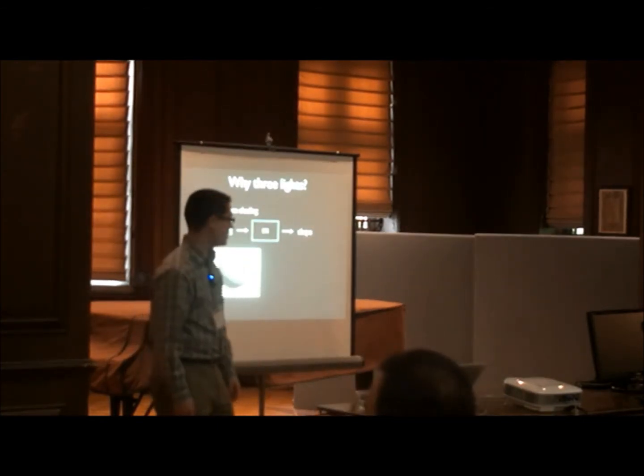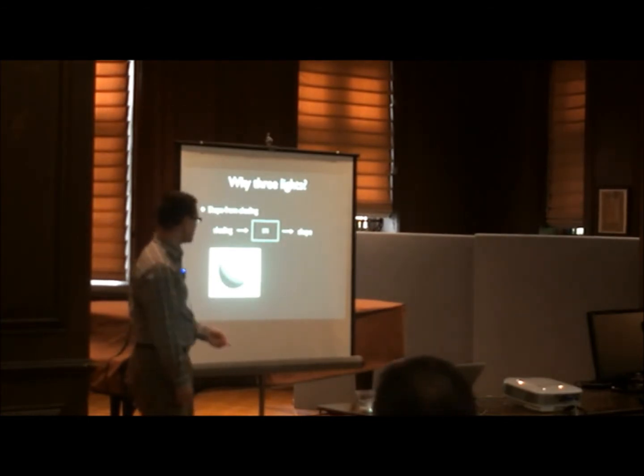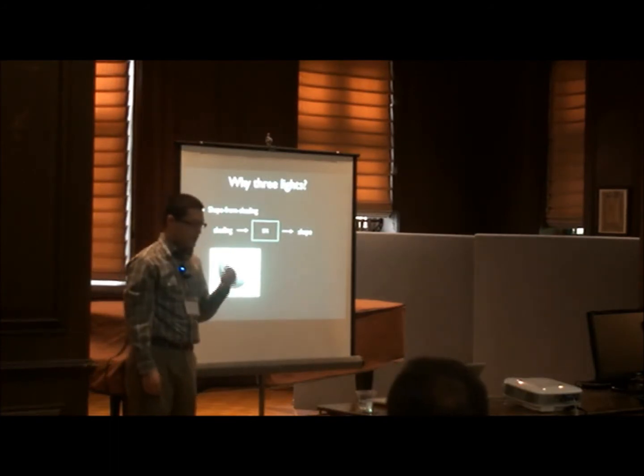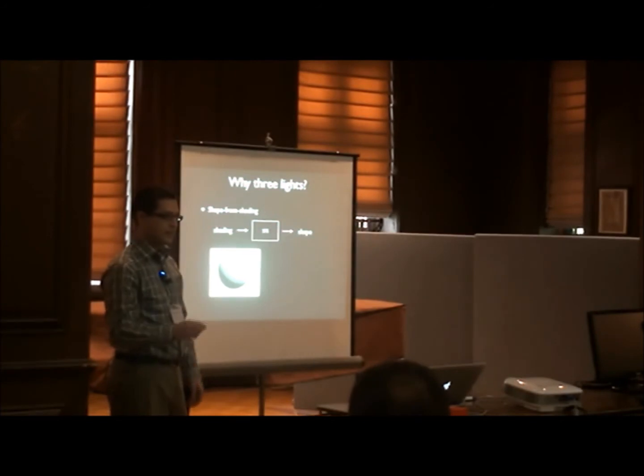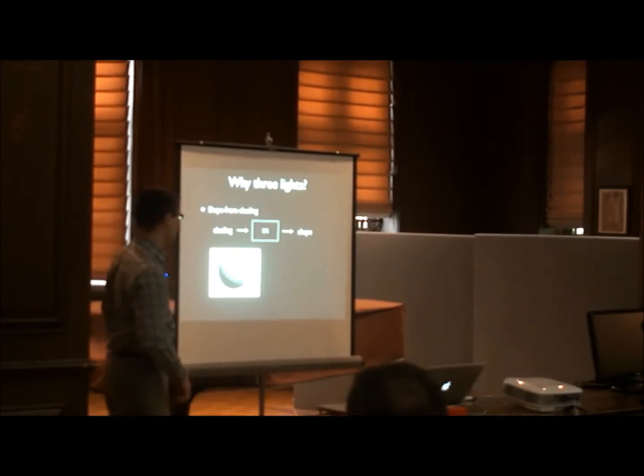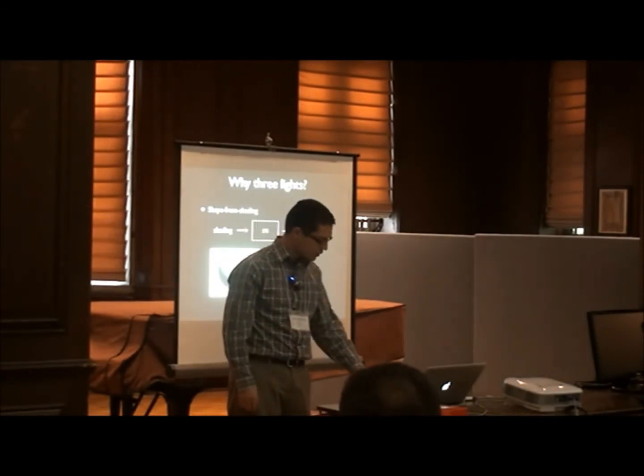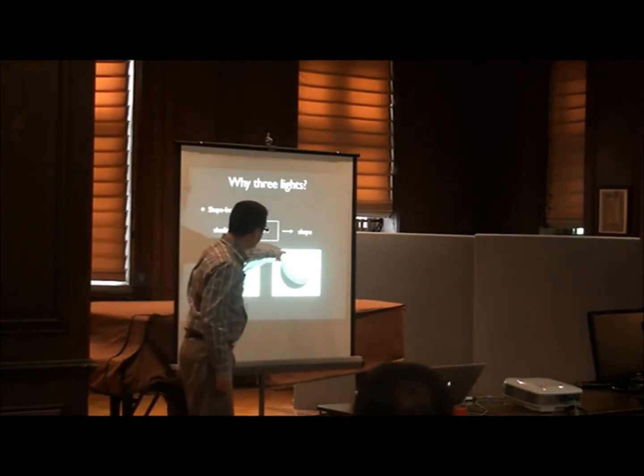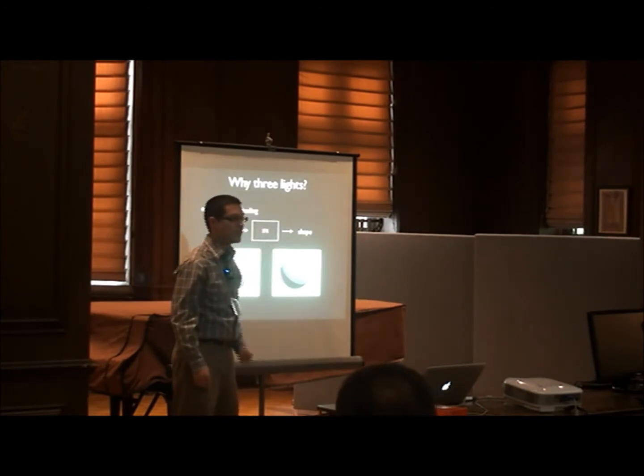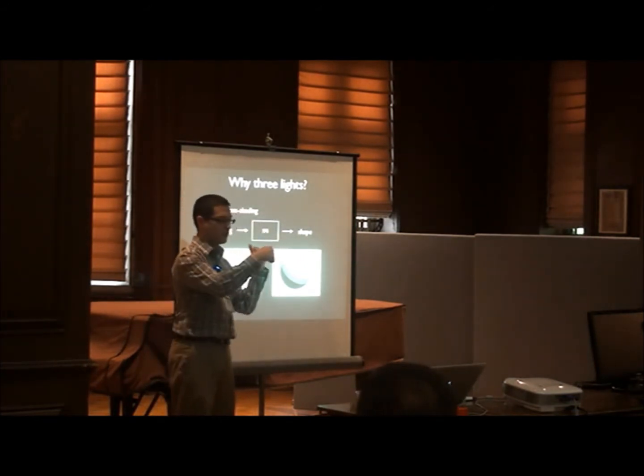This is fundamentally challenging because let's suppose we have the simplest possible shape, perhaps a sphere with a single light source. This is what you'd see with a shaded image, and the light is coming from this direction. The shape from shading algorithm needs to analyze the image, take shaded intensity values, and determine what the local surface shape is. So let's suppose you're this algorithm, running across the surface, and you encounter an intensity of 0.8 somewhere here. How do you map 0.8 back to something that has to do with the surface? It's challenging because all of the points on these curves have the same intensity. If you're at 0.8 and you're on this curve, all of these points have an intensity of 0.8, because all of these have surface orientations that make the same angle with respect to the light source. And it's that angle that determines the intensity in the image.